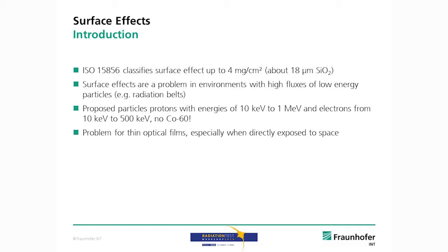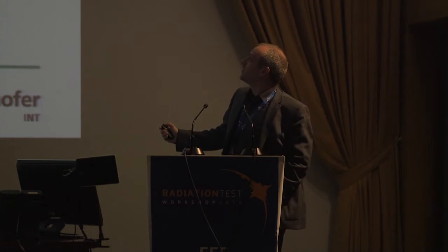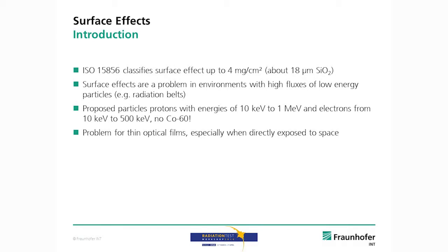If you look into surfaces, then the ISO standards classify surface effects from 4 milligram per centimeter squared. And this is, if I calculated correctly, for silicon dioxide about 18 micrometers, so 10 to 20 micrometers. Below that, you have surface effects. Surface effects are relevant for things that get in contact with very high fluxes of low-energy particles, like in radiation effects, if you're directly exposed to them.